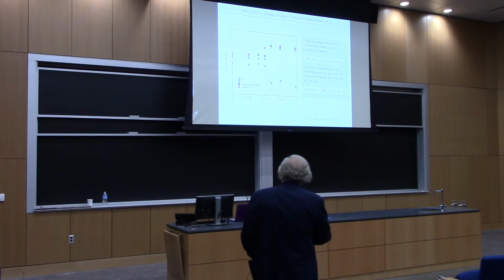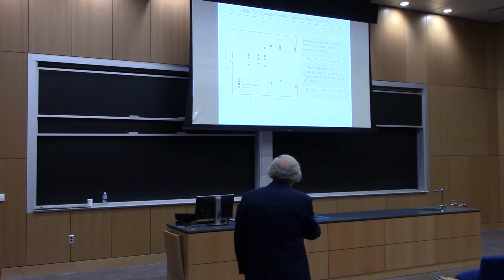And so there are data here shown for the pressure dependence in the ab plane and the z-axis, and also the volume pressure dependence. So here's the ab plane, z-axis, and then the volume pressure dependence shown here by the black points. So these all come from thermal expansion, and then the red points are the actual measurements of T sub 0 with respect to pressure. You see that they all agree very well, and that there's a very large change when we go from the hidden order phase to the antiferromagnetic phase, showing that the phase boundary certainly appears to be close to 0.11 or 0.12 for this system.